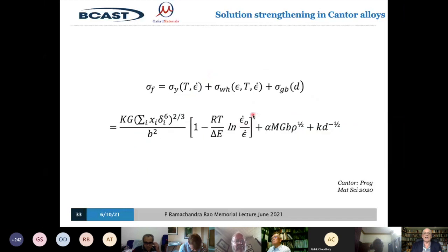The strength is determined by the sum of three components. This is the one which is the difficulty of pushing a dislocation through that strain field, which is now at the local atomic level. It's a complicated expression. And then you have to add on to it two other much better known expressions.